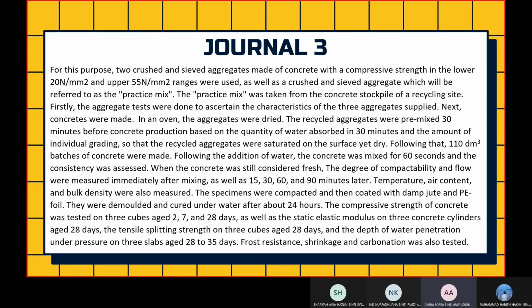Firstly, the aggregate tests were done to ascertain the characteristics of the three aggregates supplied. Next, concretes were made. In an oven, the aggregates were dried. The recycled aggregates were pre-mixed 30 minutes before the concrete production based on the quantity of water absorbed in 30 minutes and the amount of individual grading, so that the recycled aggregates were saturated on the surface yet dry. Following that, 110 dm cubed (dm3) batches of concrete were made.